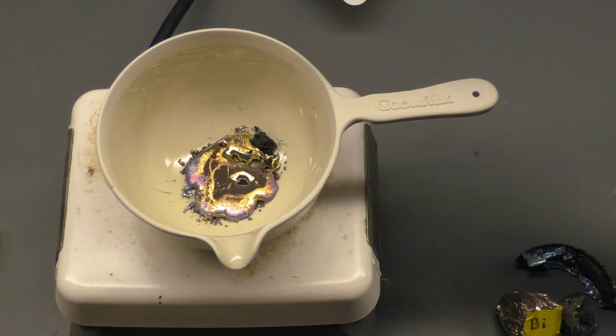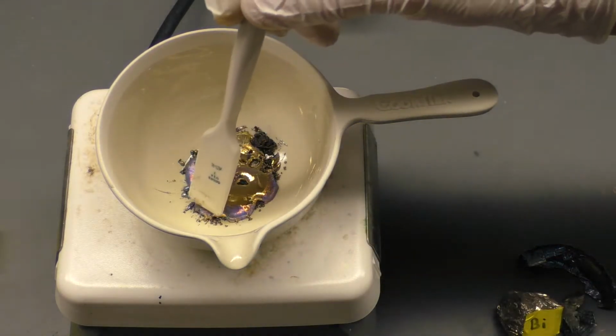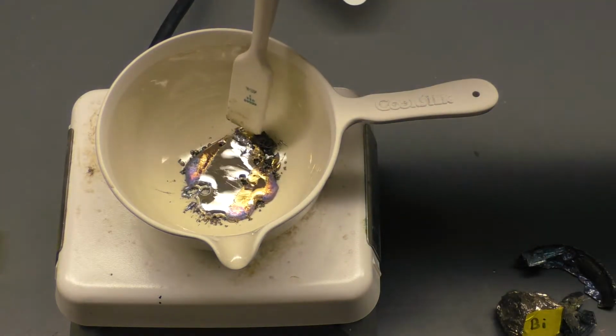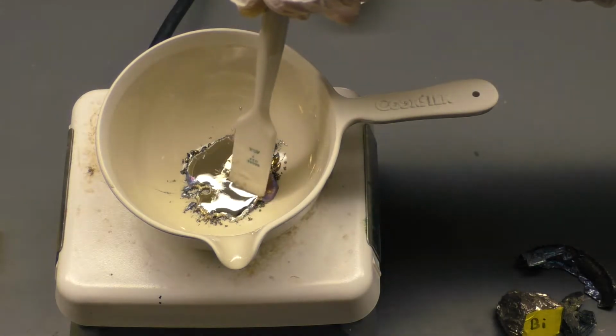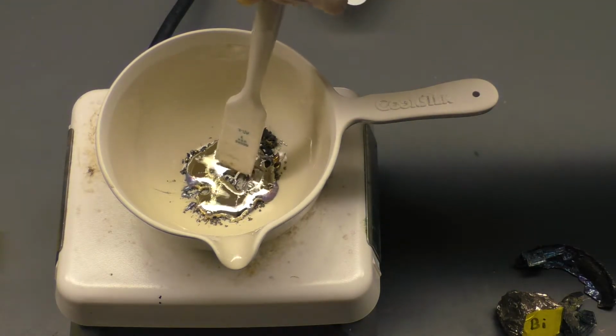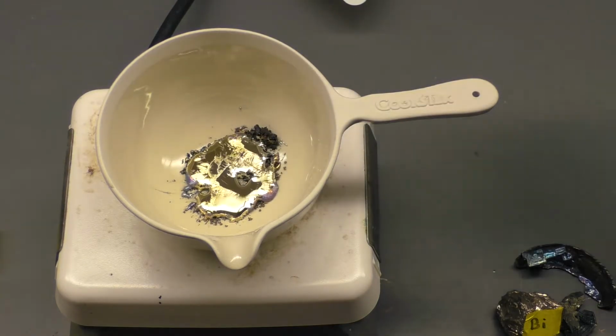And I'm kind of scraping that off the top, but watch what happens as I scrape. You can see the shiny surface of the metal underneath, and we just watch this for a second. You can see the color transformation. Just watch it. Now it's getting kind of golden. And one of the neat things about bismuth metal is that the oxide layer that forms with bismuth often produces all sorts of neat colors due to the different thicknesses of the film. So I think you can see now it's getting kind of a beautiful purpley glow.